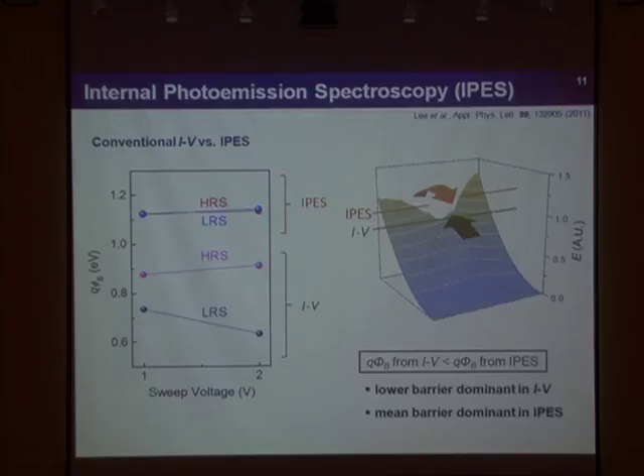When you use IV techniques, if there is any inhomogeneity of the barrier, we can regard it like a parallel-connected resistor problem, so the smaller resistance will dominate the total resistance. If there is any small barrier height region, this region will determine the apparent barrier height, and as a result we obtain a large apparent change of barrier heights.